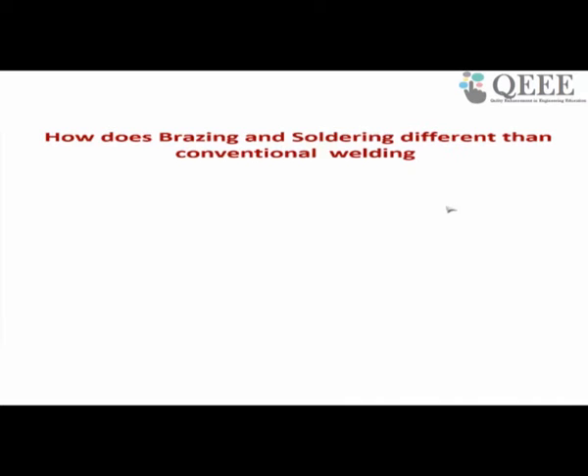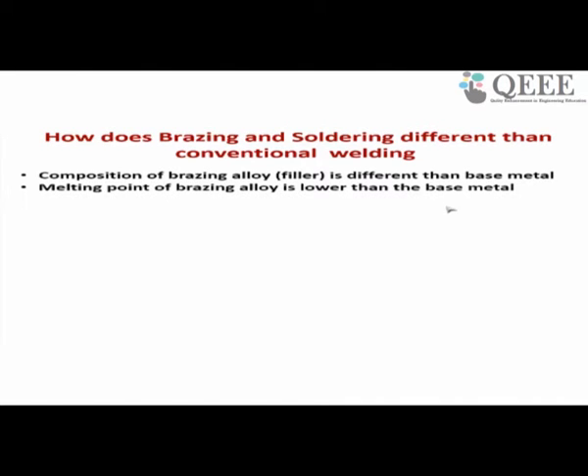So how are brazing and soldering different from conventional welding? In conventional welding, you have to select a filler material in such a way that the composition of the filler material should be exactly similar to your base material. Since you have to melt both, the melting point of the filler material as well as the base material is almost similar, because you are using similar composition in conventional welding.